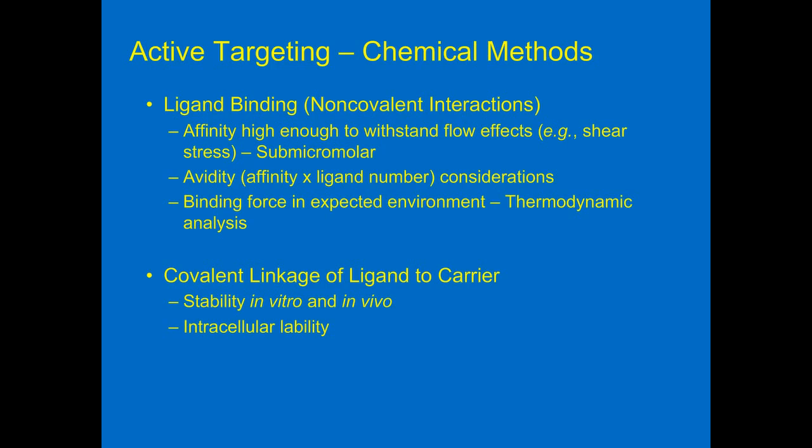Avidity is the actual aggregate affinity of a number of ligands that are actually binding to the target molecules on a surface. And of course, this is the product of the monomolecular affinity and the number of ligands on a nanoparticle that are actually binding to the target on a surface.